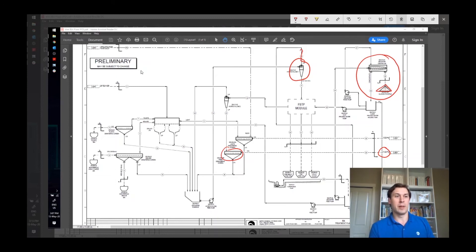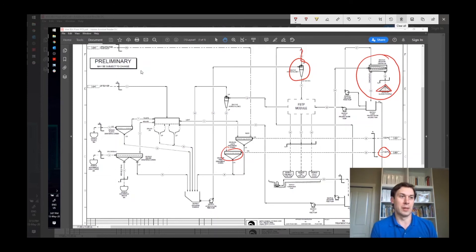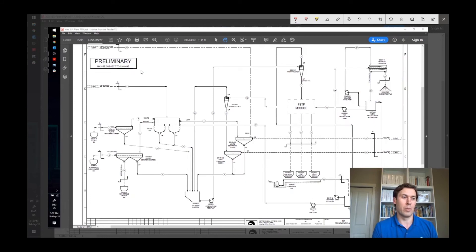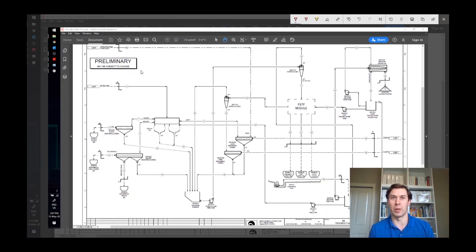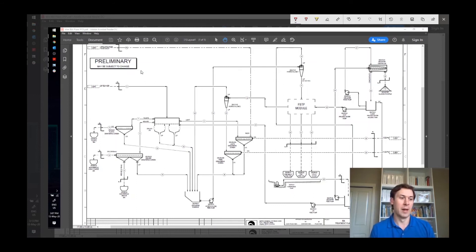So what's nice about this? There are a few things. We end up removing the slimes, which are generally what needs to be removed anyway to create an aggregate product. Generally the minus 63 or so, depending on the jurisdiction will cause problems with aggregate spec.